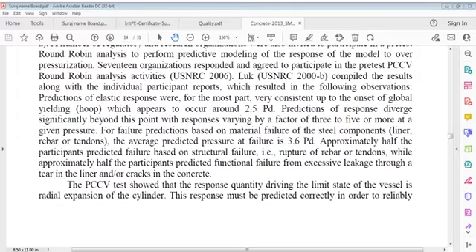Predictions of elastic response were for the most part very consistent up to the onset of global yielding of the hoop, which appears to occur around 2.5 PD. Predictions of response diverge significantly beyond this point, with response varying by a factor of 3 to 5 or more at a given pressure.